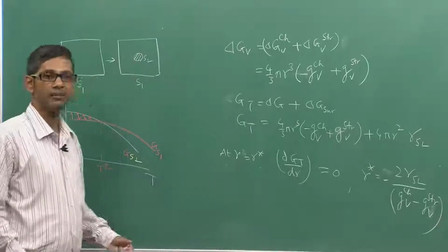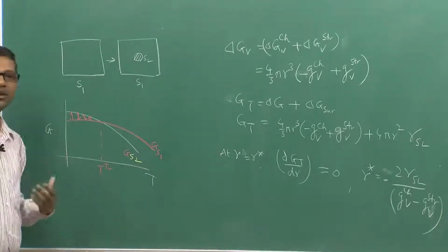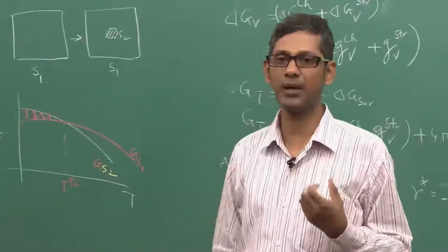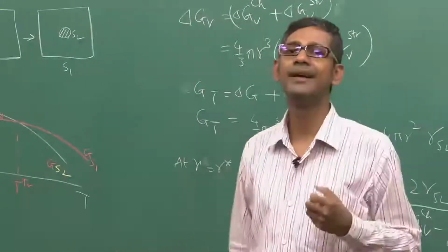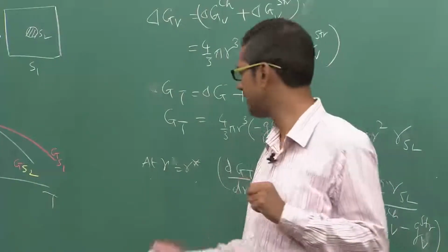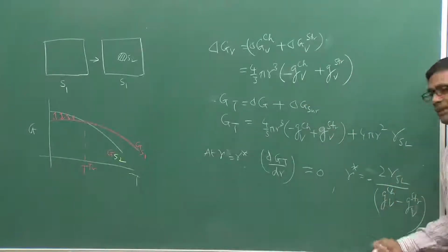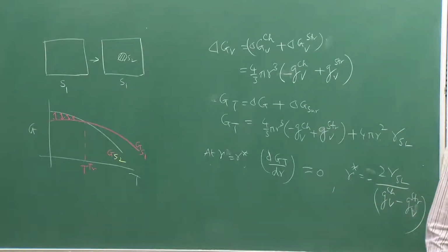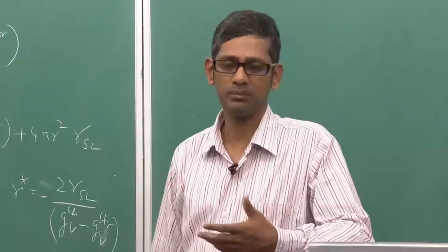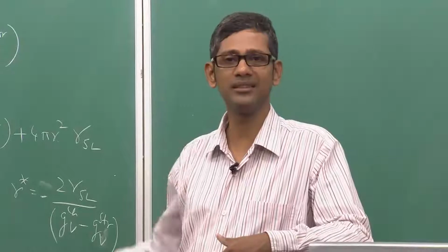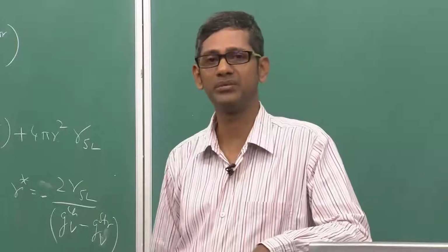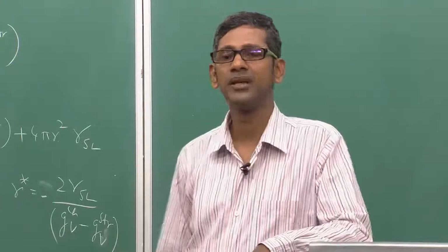So, that is the main thing in a solid. Therefore, in solid to solid transformations, the critical size nuclei, or embryo rather, which will become a nucleus later on, is bigger than in a liquid to solid transformation. That is the major conclusion you can draw here. And this is very important because we will see in our examples, in different types of solid to solid transformations, that this is a strong aspect. Strain will be present inherently in many of the solid to solid phase transformations.